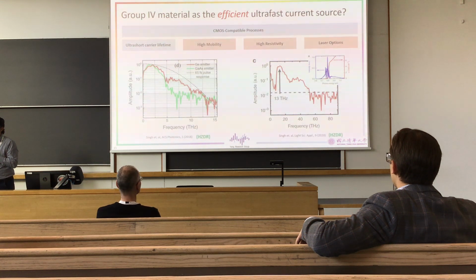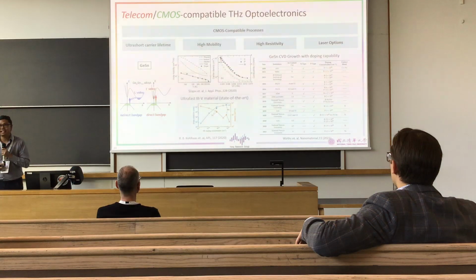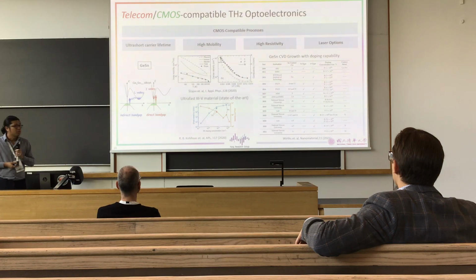So we're thinking, okay, how about going deeper? Let's go with germanium tin. If you go with germanium tin with higher tin composition, you can shrink the gap. This is good, it means you have better coverage of the wavelengths, and you're unlocking many laser options. Most importantly, if you increase the tin composition, it will transfer from an indirect bandgap material to a direct bandgap material. And the mobility is good. It is comparable with the ultrafast III-V materials, the state-of-the-art ones. The better news is you can use a CVD tool to grow the germanium tin film, and this CVD tool is used in the industry. So it's very good.